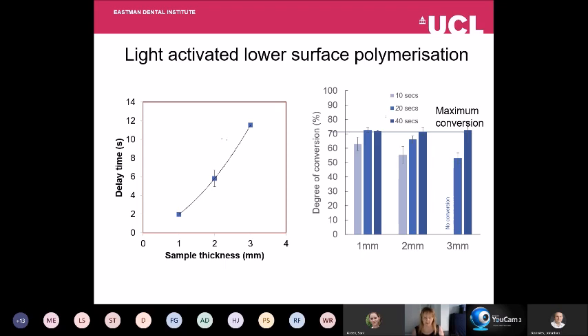We can look at what's happening at the bottom of samples of 1, 2, or 3 millimeters depth. What we've found is with the smart composite, if we have a 1 millimeter sample, there is a 2-second delay before there's any reaction. If we double the thickness, there's a 6-second delay. And if we go to 3 millimeters, there's a 12-second delay before there is any reaction.